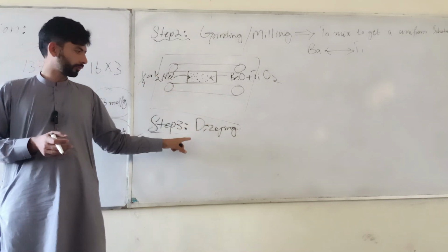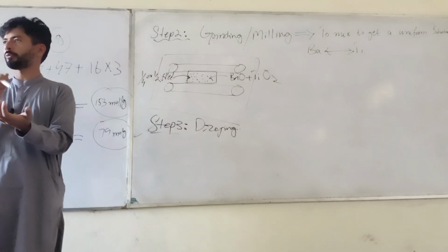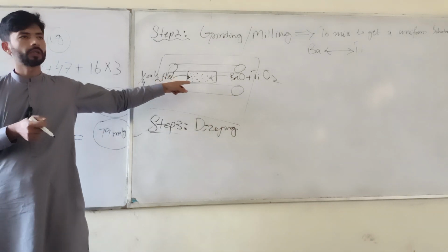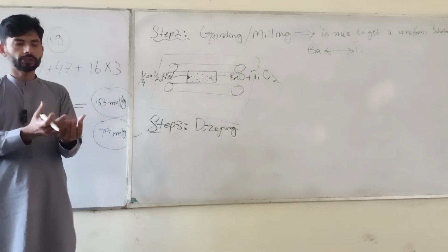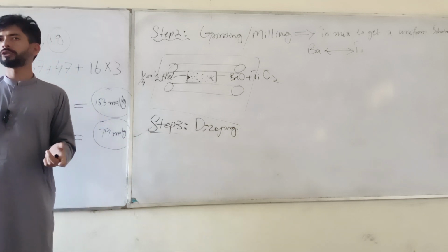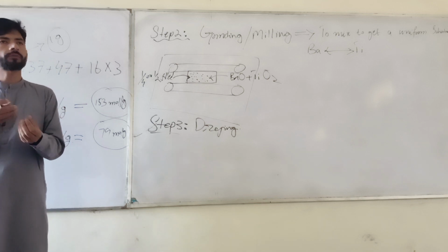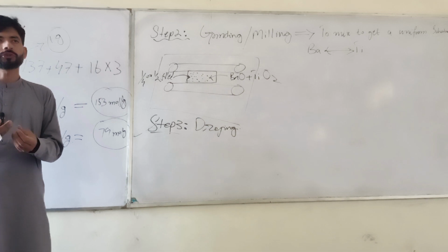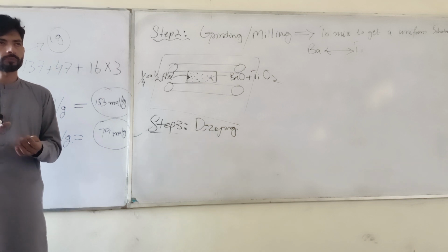But before going into step number 3, you have to wash this media with the same kind of liquid. For example, if you are using acetone here, then wash those balls with acetone. Get the solution in a beaker and put that beaker in a drying oven at 90 degrees C or 80 degrees C overnight or for 12 hours, because after that you will get a powder which is free of moisture, which does not create beads, which is almost uniform.